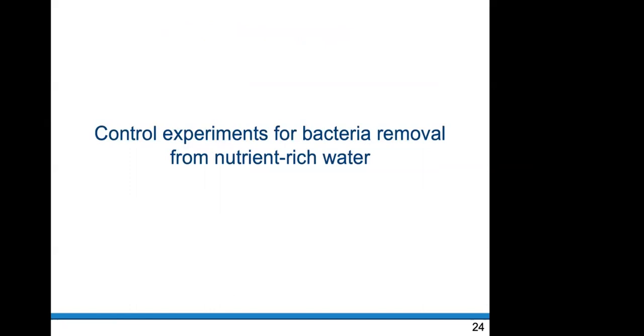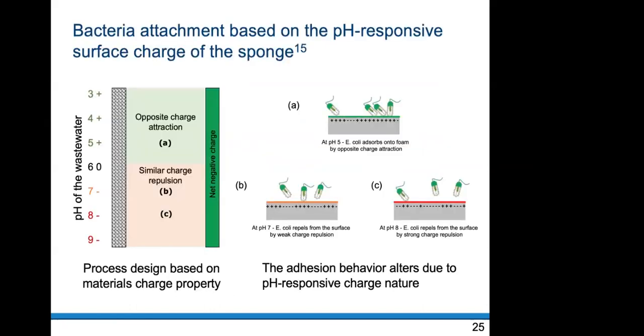So next, we have done some proof of concept experiments where we took these pristine sponges and looked at how they would measure up at removing bacteria from nutrient-rich water. As I said, the sponge has both carboxyl and hydroxyl groups. Because of that, depending on the pH of the water, they can switch between negative and positive charges. For example, for this specific material, at acidic conditions it is more positive, and at basic conditions it is more negative.